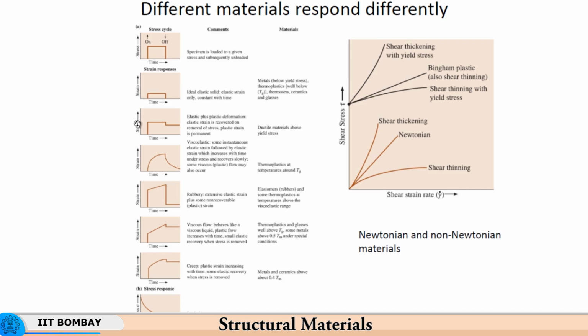So, the rate of change of strain rate therefore continues to drop, because the viscous response of the material results in hardening of the material, and therefore the strain rate continues to drop. In the initial phase the strain rate was 0, and then the material had to start from the 0 strain rate. So, immediately as the stress was applied, it responded with a very high strain rate, but then as the strain rate was high, the hardening of the material was also very high in response to the